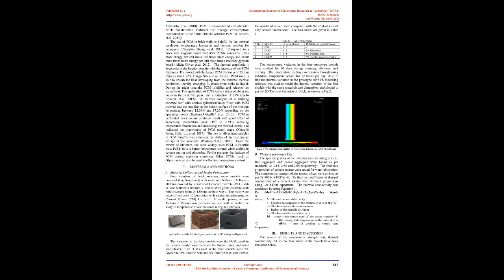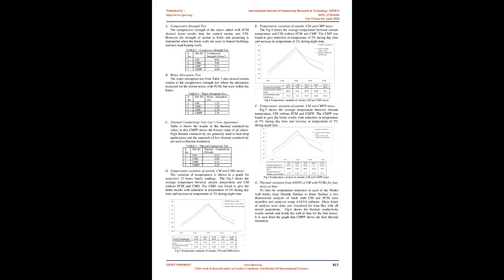Alicia Oliver et al., 2012: The thermal amplitude is decreased in the interior domain with the increase of the PCM thickness. The model with the larger PCM thickness of 25 mm reduces about 22%. Tiago Silva, et al., 2012: The PCM used is able to absorb the heat developing from the external thermal conditions, thereby changing its phase from solid to liquid. During the nighttime the PCM solidifies and releases the stored heat. The application of PCM led to a delay of about 6 hours in the heat flux peak, and a reduction of 25%.